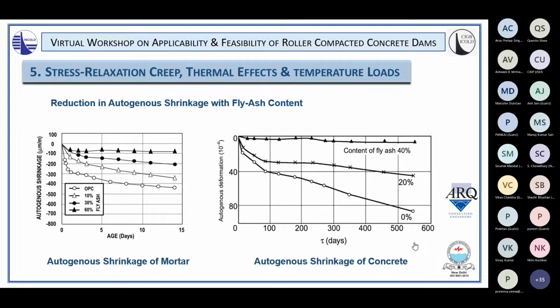If we look at this then into concrete on the right-hand side, we have a situation where a 0% fly ash might give something like 85 microstrain of autogenous shrinkage at around about 550 days. Whereas that number is reduced to something under 10 microstrain when just 40% of fly ash is added.